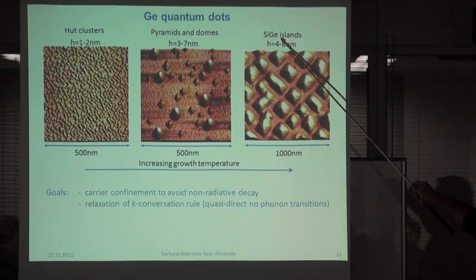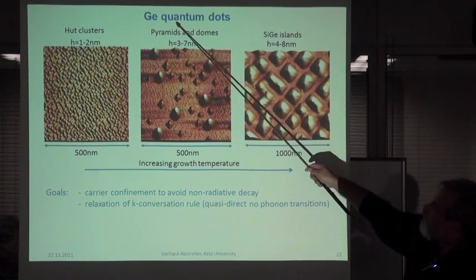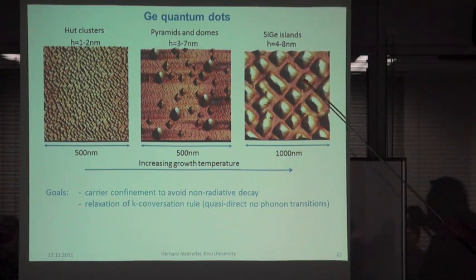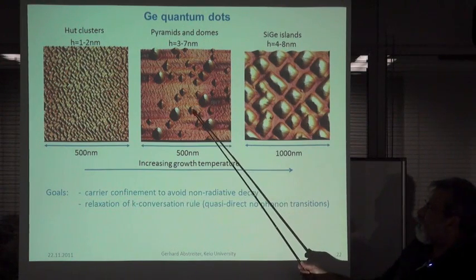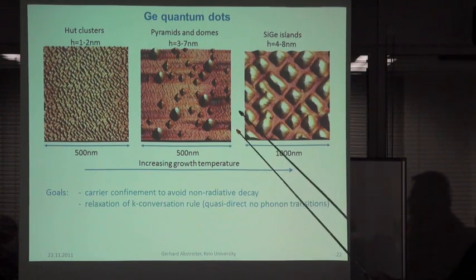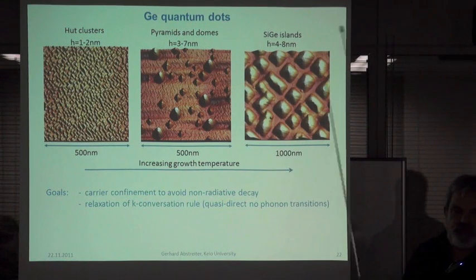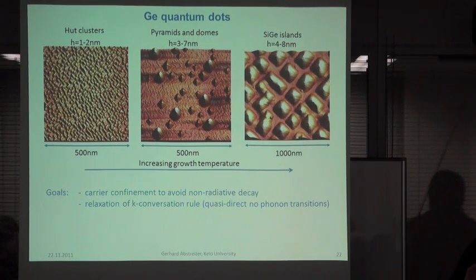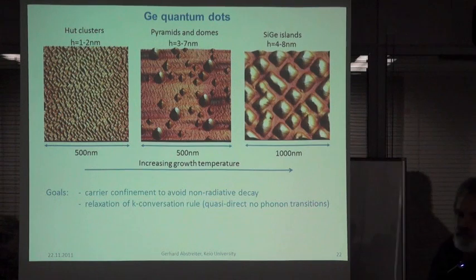And if you go to silicon germanium, so you don't go to pure germanium, you can also grow very large and rather flat islands. Here the scale is changed. Each island has maybe 100 nanometers, let's say, length and width, and the height is 4 to 8 nanometers. This may have an advantage compared to these dots for optical properties, because these dots, high germanium in silicon, have typically a type 2 band offset, which means the electrons are in the surrounding silicon and the holes in the germanium, so it's spatially indirect, while this has a type 1 band offset.